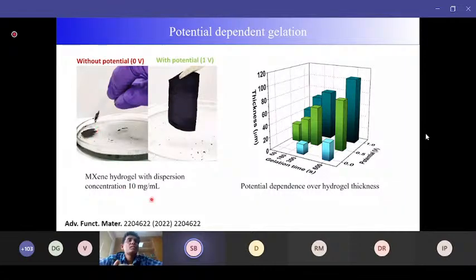We use the 10 mg per ml solution, much lower concentration, and as you can see the gelation rate is so high, because in this case within 60 seconds we can get a sufficiently thick gel. But if you do not use the voltage, you cannot get any gel, just a slight deposition over there.